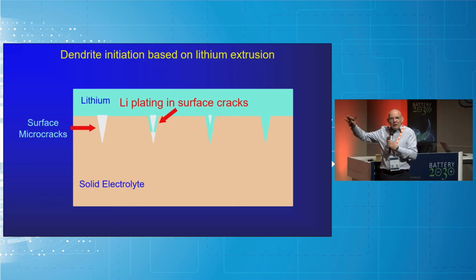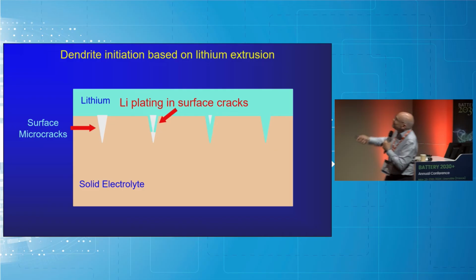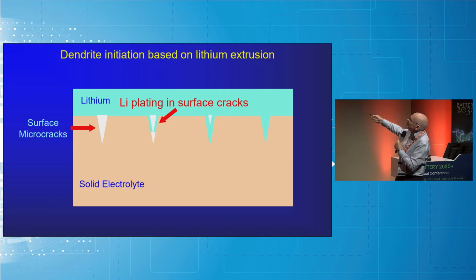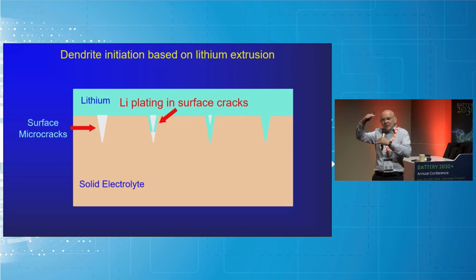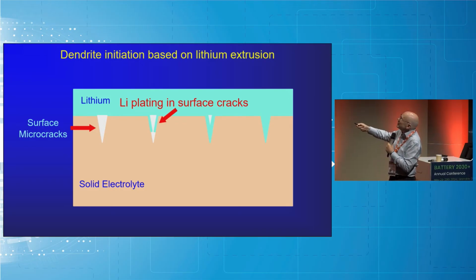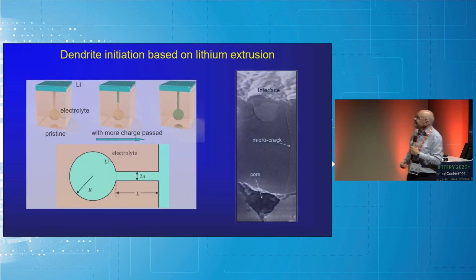So when you start plating lithium, when you charge your battery, the natural place for that to occur are these points here, okay? And then the lithium will grow down into these crevices. Remember, this whole thing is under stack pressure. So to nucleate lithium here is harder than to nucleate lithium here. So you fill these crevices first.